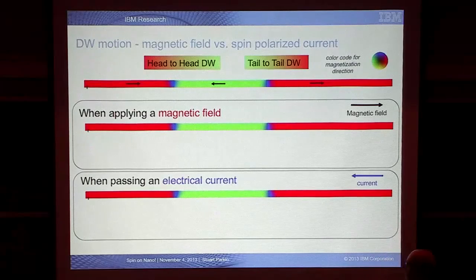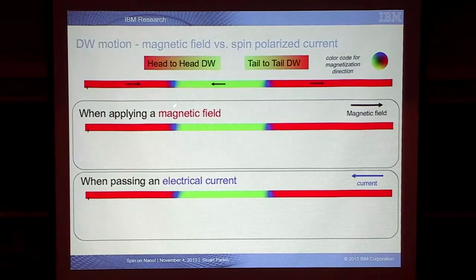So now why is it interesting for this racetrack? Let me show you that by simulation. Here, for example, is a homogeneous magnetic wire. The colors represent the direction of the local magnetic moments. Red is pointing to your right, green to your left, blue is pointing up, and yellow will be down. Now the basic concept is this. We have a uniform magnetic wire, and here is this domain wall I mentioned. These are two regions where the magnetic moments are pointing north pole to north pole.